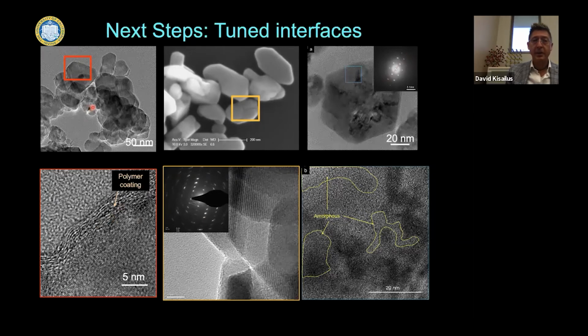So this is actually a silicon carbide particle with some polymer coating that we're using to place on top of carbon fiber composites, for example, to make coatings like this to protect the underlying layer. But we're also now synthesizing mesocrystalline particles where we can tune these interfaces and get low angle grain boundaries, where we can add additional toughening by making mesocrystalline particles.